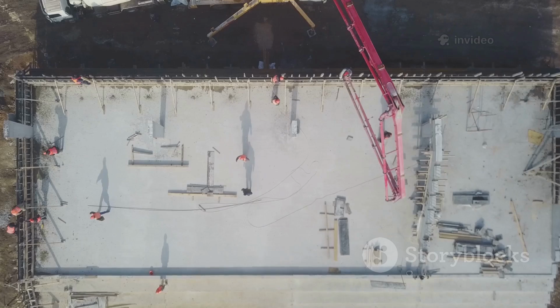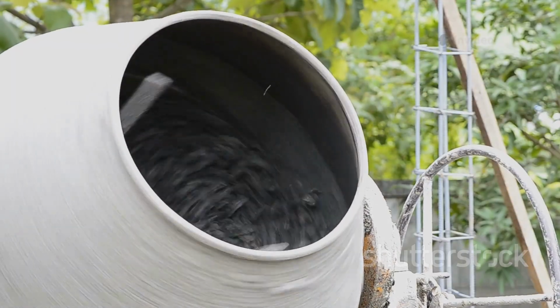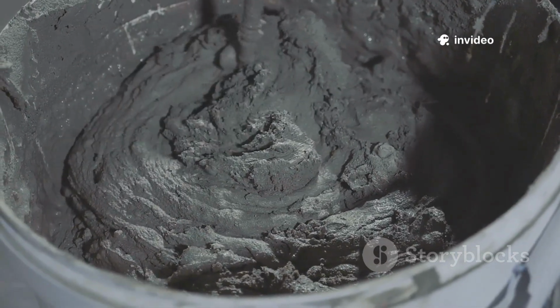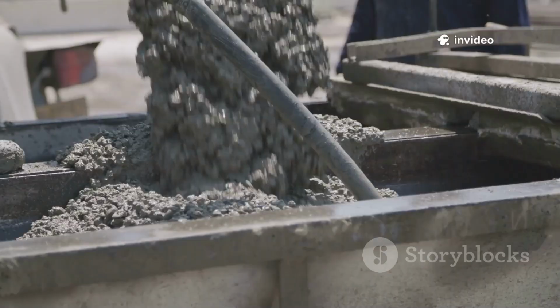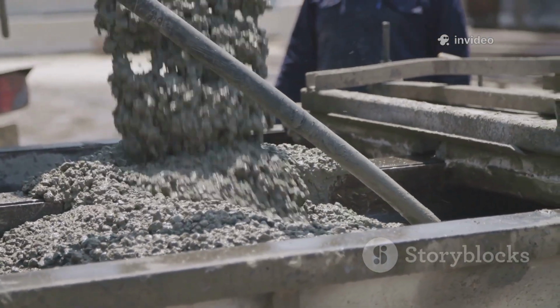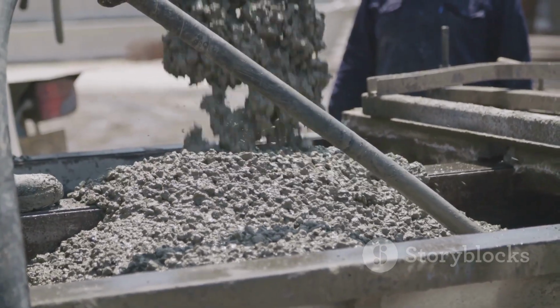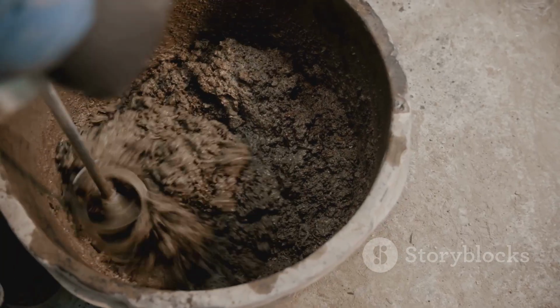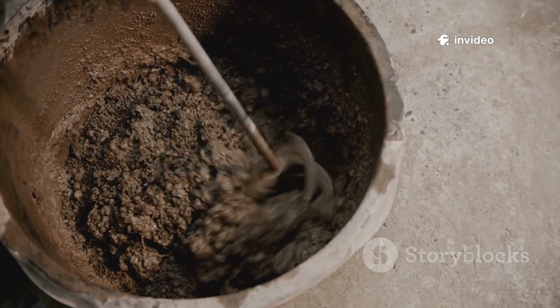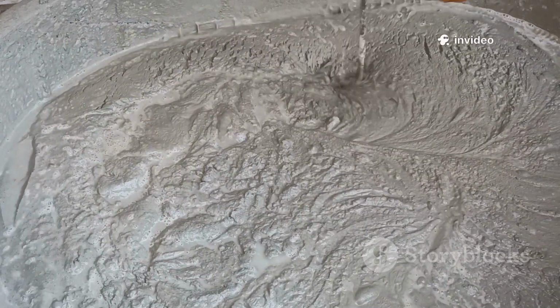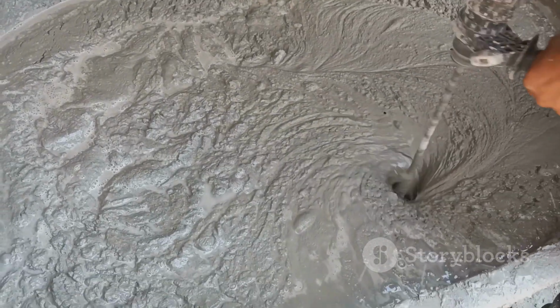The aggregates provide the bulk and volume, making concrete a much more economical material than if it were made from pure cement. The water is the catalyst that starts the whole process. When it is added to the cement, it triggers the hydration reaction I mentioned earlier. This is not simply a case of drying out. It is a complex chemical process where new, interlocking crystalline bonds form throughout the mixture. This crystal network grows around the aggregates, locking them into place and creating the dense, durable matrix of concrete. The strength of the final concrete depends heavily on the ratio of water to cement. Too much water creates a weaker concrete, while too little means the mixture won't be workable enough to place properly.